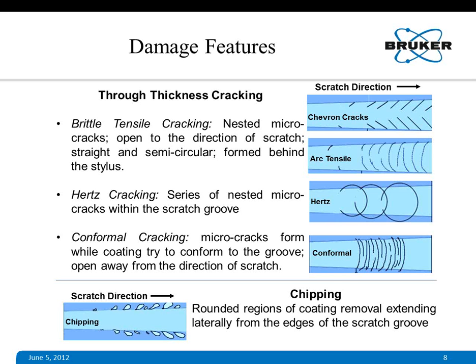One is cohesive failure, like through thickness cracking, such as brittle tensile cracking. These types of cracking can have nested micro cracks open to the direction of scratch. They can be straight, like chevron cracks, or they can be in the form of an arc, as an arc tensile crack, as shown on the right side of this view. There can be hertzian cracking, a series of nested micro cracks within the scratch groove.